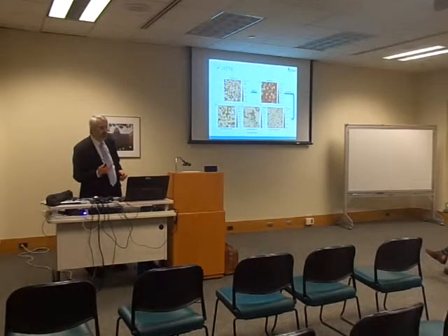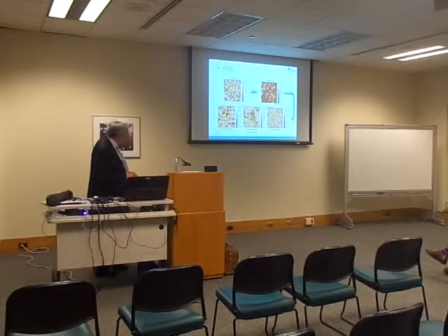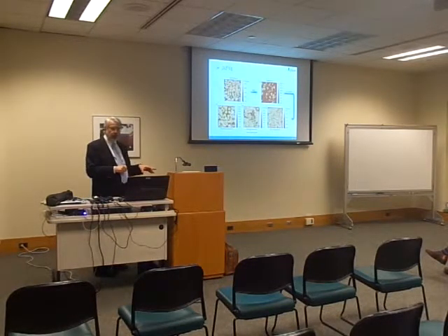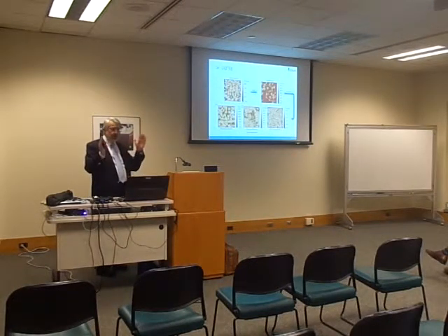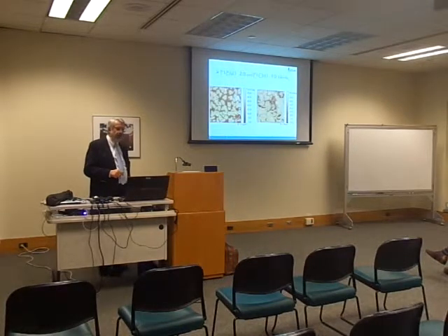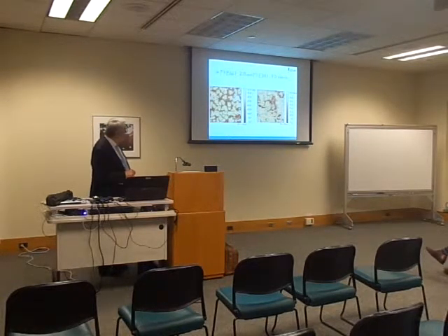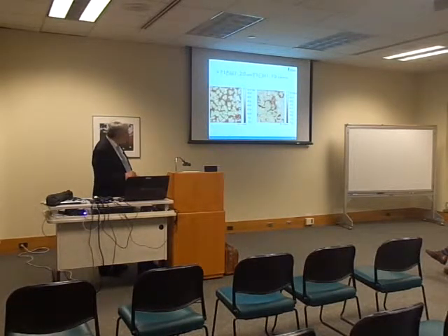But depending on the type of rejuvenator, starting from this end, for some particular rejuvenator, after its application, we managed to restore the structure back to more or less the same as the original. For other types of rejuvenators, we got some very different looking pictures. Look at this. And magnification, comparing the two, is here. This is one particular type which produced a good restoration and corresponding mechanical properties. This is another rejuvenator, but look at the difference. It was nothing like the original.